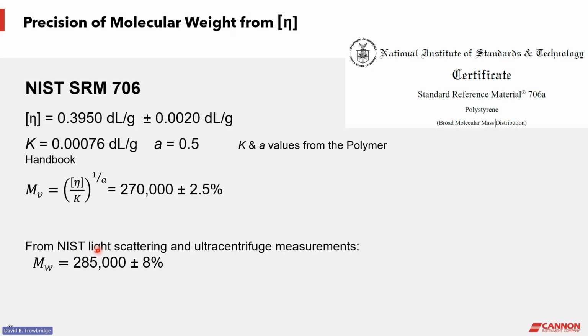And then NIST, for the same material, the polystyrene 706, did additional characterization measurements using light scattering and ultracentrifuge, and the molecular weight they got had an uncertainty of 8% using these other techniques. So the point here is this uncertainty. The IV, the molecular weight from the measured IV was much less uncertain than it was for the other techniques that gave a molecular weight measurement. And so that indicates a strength for the IV measurement.